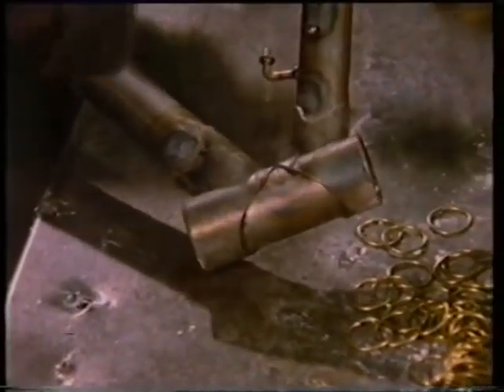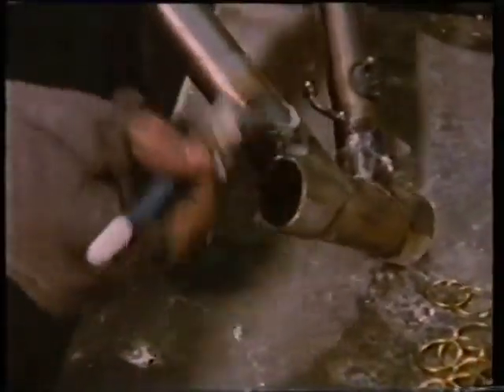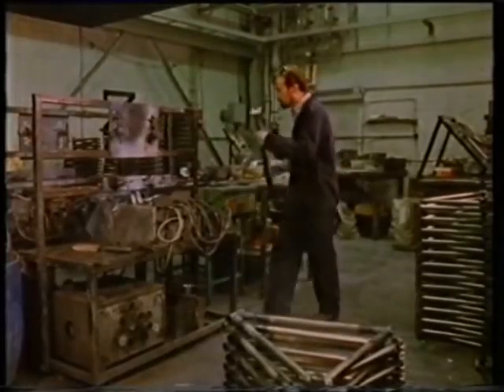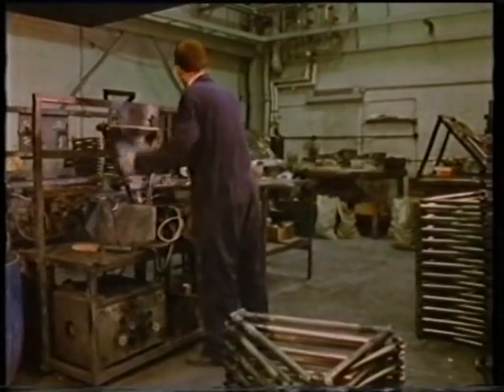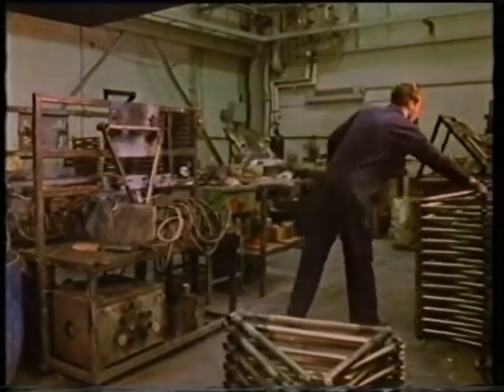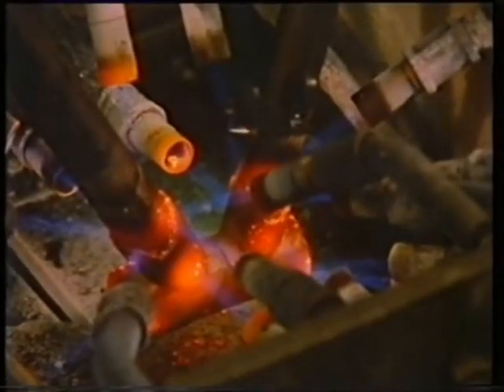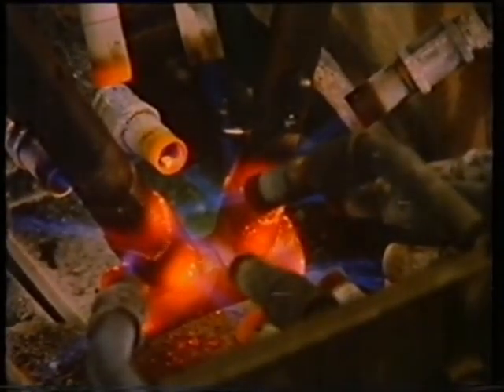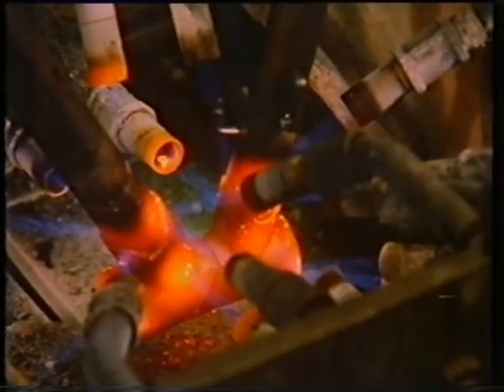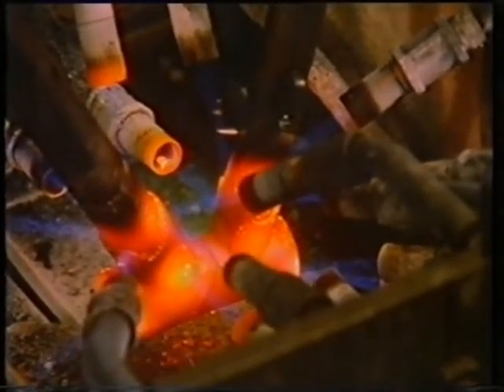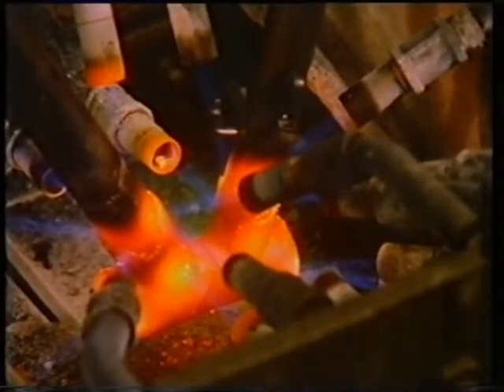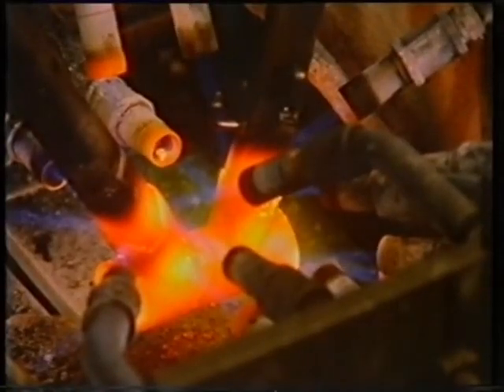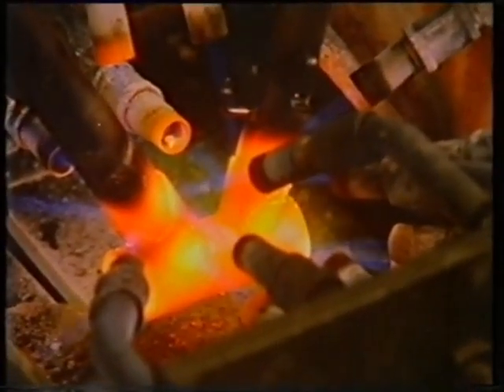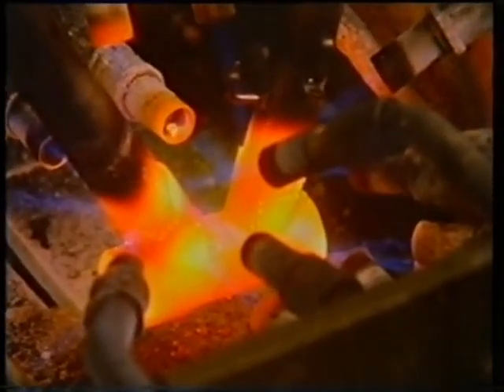The remaining preforms are added and the joints are then fluxed. The frame is then hung over a timed gas jet, where this joint is heated for approximately 2 minutes. When the temperature reaches around 950 degrees, the brass inserts melt and the brass rises by capillary action to fill the joint. But at this temperature, the copper tack weld is still solid, and so that holds the frame together.